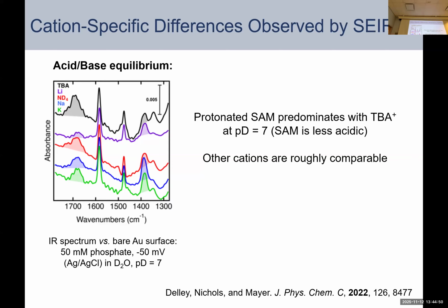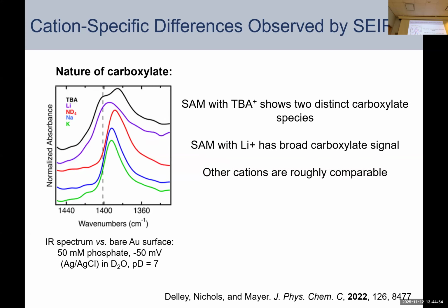Many of the other cations are roughly comparable, looking at the relative integrations of these peaks. Another interesting feature is that the peak maximum shifts quite a bit depending on cation identity. And so this goes to show that the cations are actually specifically interacting with the carboxylates at the surface. So you can see that, for example, the tetrabutyl ammonium trace here in black actually has two different maxima, suggesting that there are two separate identities for the carboxylate species on the surface. The lithium example is really broad. That's this purple trace here. So that's maybe suggesting a large number of different carboxylate interactions between lithium cations, and possibly also the role of water solvation here.